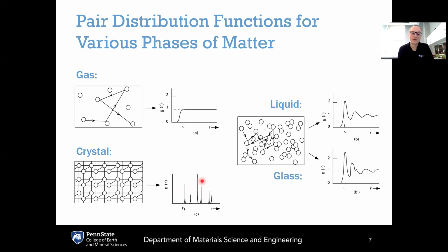If you have a polycrystalline material, then you start to lose correlations anytime you cross a grain boundary and go from one crystal to the neighboring crystal, especially if there's a change in orientation.